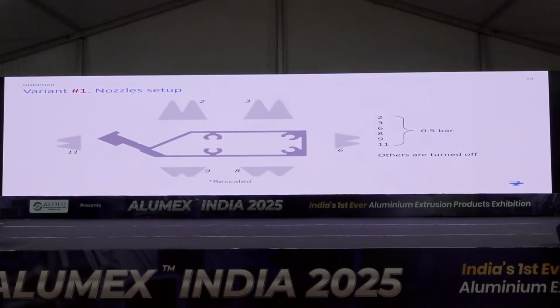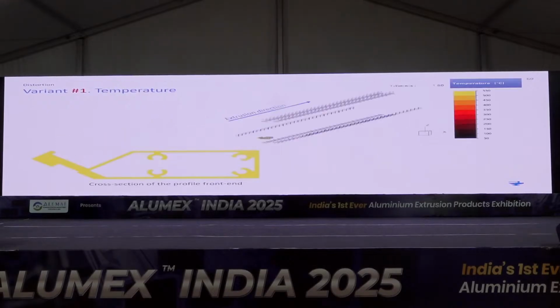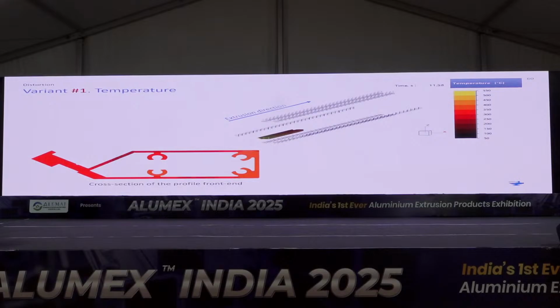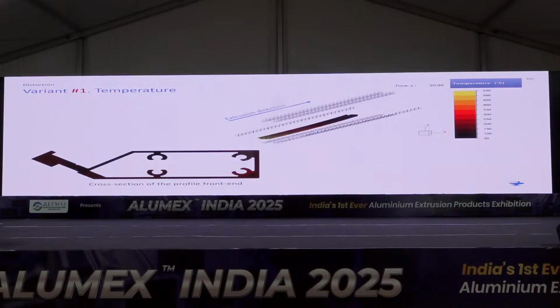Once you have simulated the extrusion process, you can set up the quenching station parameters like flow rate in a particular nozzle or pressure, which typically fully determines the intensity of the cooling. Then you simulate the quenching process, checking if the cooling process is good enough, considering the displacement of the profile, the thickness variation, or whatever is of interest, maybe even grain size.